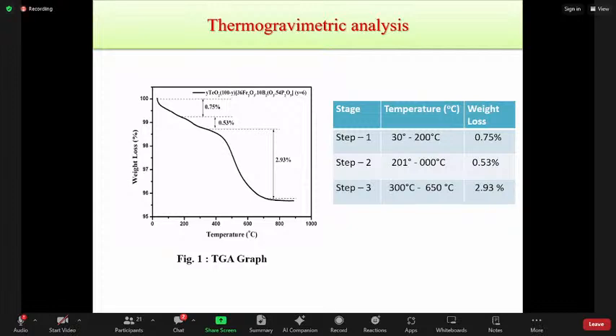The weight percent loss is calculated by using thermogravimetric analysis. In the thermogravimetric analysis, three steps are observed for the weight percent loss. In the first step, 0.75% weight loss is observed between 30 and 200 degrees Celsius, due to the evaporation of residual trapped water. Then in the second step, 0.53% weight loss occurs between 200 and 300 degrees Celsius due to the volatilization or residual oxidation.